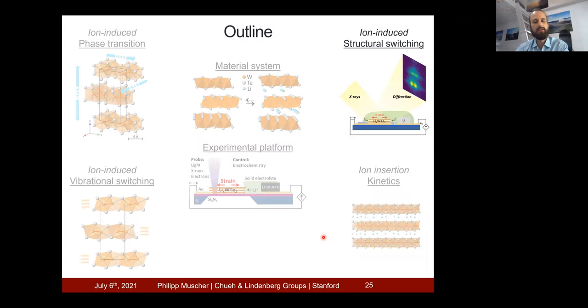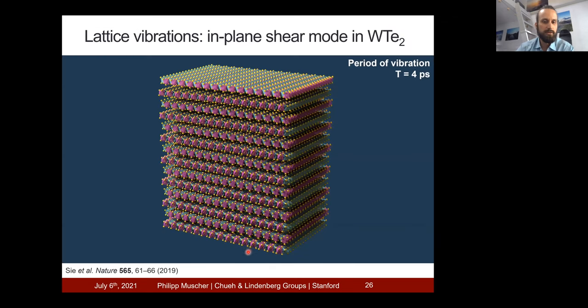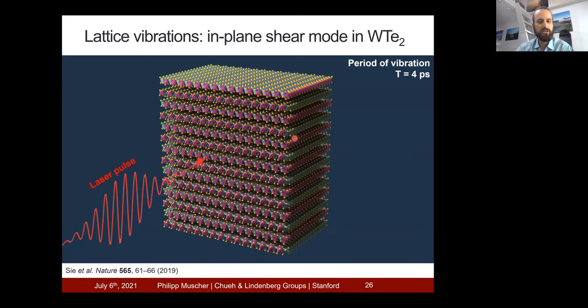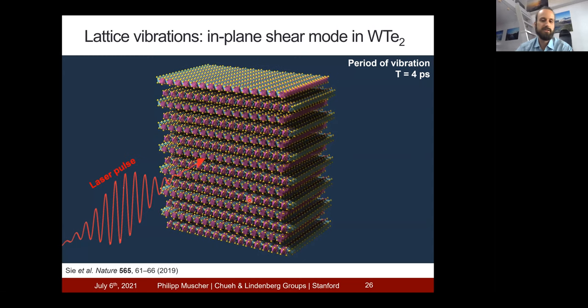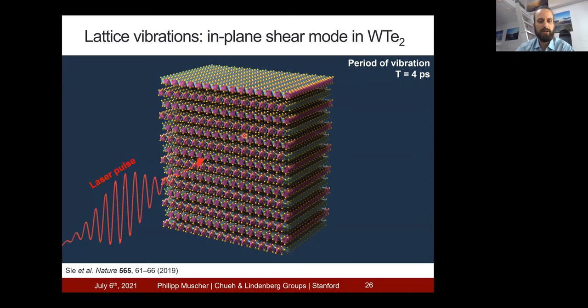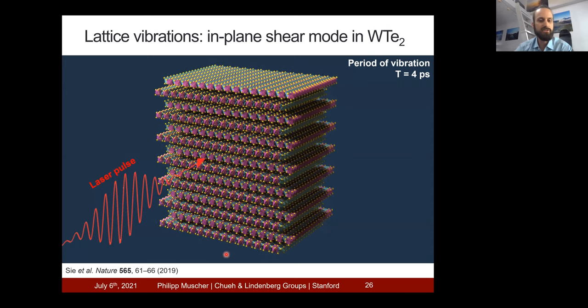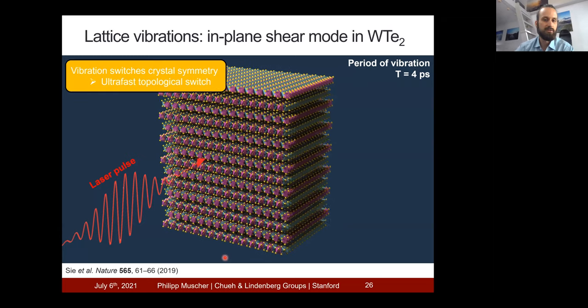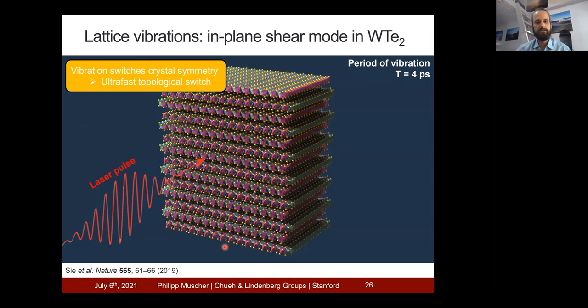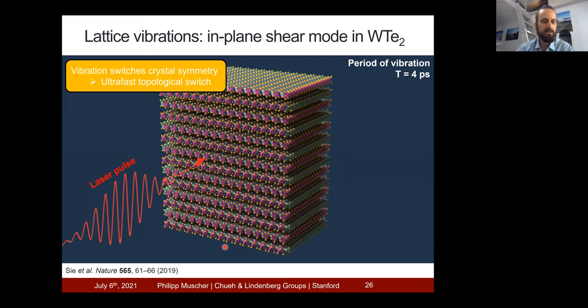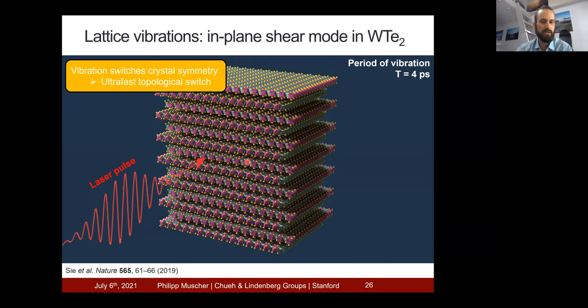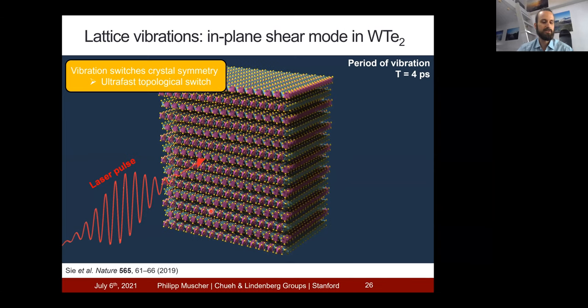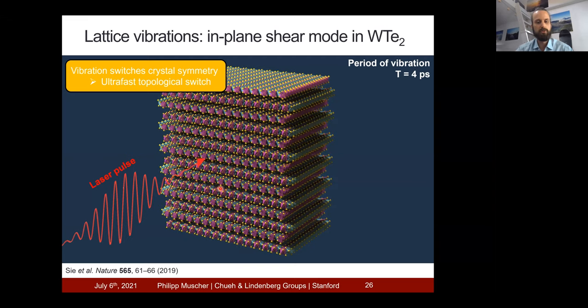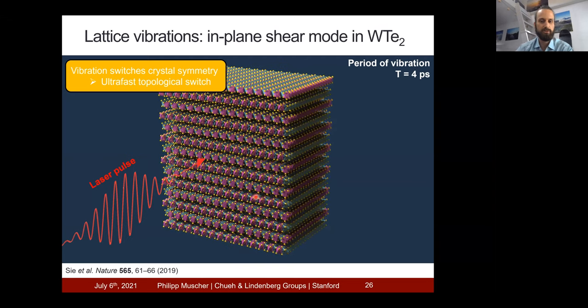So with this on structure switching, I want to come to vibrational switching. This is a depiction of tungsten ditelluride, and we can launch a laser pulse that hits it. It turns out this laser pulse excites an in-plane shear mode in the material. And this shear mode is very interesting, because the crystal symmetry of the material is switched as it shears between a structure with inversion symmetry and a structure without inversion symmetry. This symmetry is linked to all the topological quantum properties. So this vibration is actually an ultrafast topological switch.